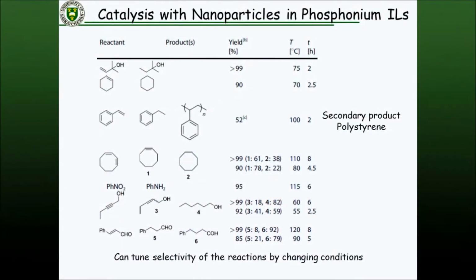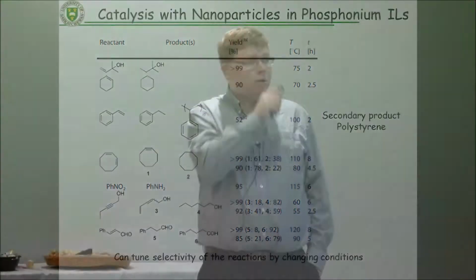As an example, we started out looking at hydrogenations of all different types, all the very simple hydrogenations, to looking at possible selective hydrogenations. And all the way through, you get a very strong hydrogenation catalyst. This is with palladium nanoparticles, by the way, in the ionic liquids. And depending on the conditions, you can sometimes get selectivity, for example, in the diene to the monoenes that I have there. But that's mostly just on the catalytic conditions themselves, what temperatures and how long you actually run the catalytic reactions at.